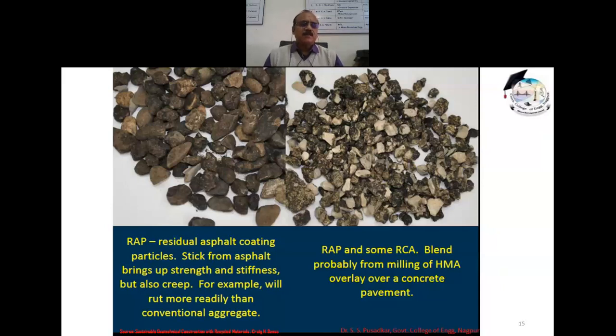Okay. The other material is the residual asphalt coated materials. When I am removing the bituminous road, definitely we will get these coarse aggregates which can be used. The stick from asphalt brings up strength and stiffness, but it also has a creep problem. So it creeps more rapidly than the conventional aggregate. So we should find out the proper place for the utilization of this recycled aggregate in the construction of pavement. So this RAP and some RCA can blend, probably from milling of HMA overlay over concrete pavements.